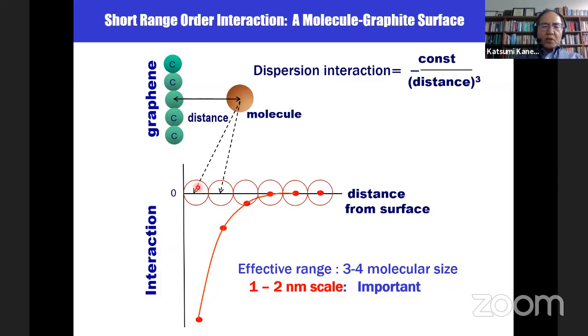At the monolayer position, the interaction potential is very deep, very highly negative. But for the secondary adsorbed molecules, the negative, attractive interaction is not so much, and for the third and fourth, almost nearly zero, and five, almost nearly zero. If the target molecules, nitrogen molecules, are around 0.35 nanometers, in such a case, in order to get efficient dispersion attractive force, we need some nanostructure. A 1 nanometer scale structure is very important for getting the effective dispersion attractive forces.